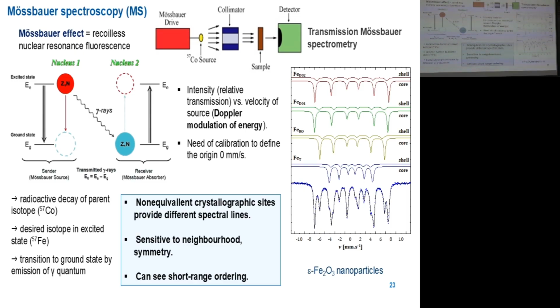I think that we don't have enough time to go into the details, but I will mention that this technique is usually measured in the transmission geometry, and the collected spectra look like this. It is the dependence of the intensity on the velocity of some source of the gamma rays that is vibrating, or moving forward and backward, just to do the energy modulation by the Doppler effect to modulate the gamma beam to cover different energies of the transitions.